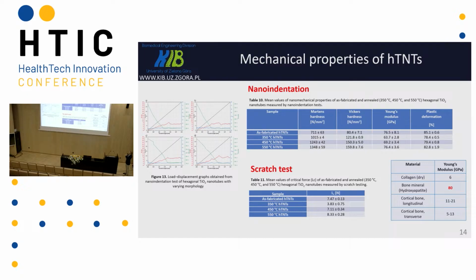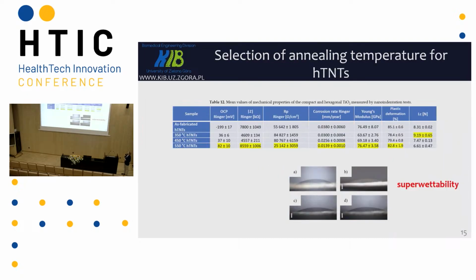The Young modulus was significantly lower, and when we use the higher temperature and obtain the mixture of anatase and rutile, the Young modulus is almost at the same level. The hardness of this material increases, so this is our observation. And the critical load also increases. So, based on this result, we chose the temperature 550 for the next step of our research.